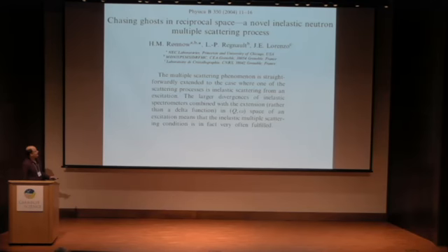Okay? And you might think, well, why is that? Well, in fact, for neutron scattering, you have larger divergences in a neutron spectrometer, and combined with the fact that these inelastic cross-sections have a large extent in Q and omega, they're not Bragg peaks. They're not delta functions in energy and Q. They're actually very big. That makes it true that these inelastic multiple scattering conditions are very often, in fact, fulfilled. Okay.